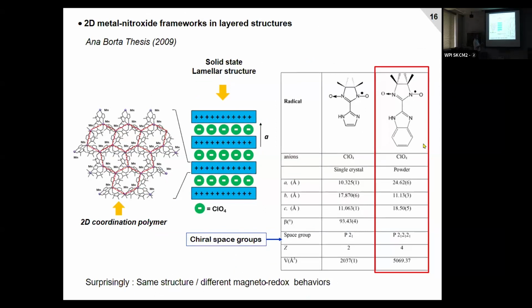So if we make the nitronyl nitroxide with benzimidazole here, in fact it's not possible to grow crystals big enough for X-ray diffraction on single crystal. We need powder diffraction, and we have an orthorhombic system. One thing very interesting is that most of the compounds with this ligand always crystallize in almost approximately the same structure.